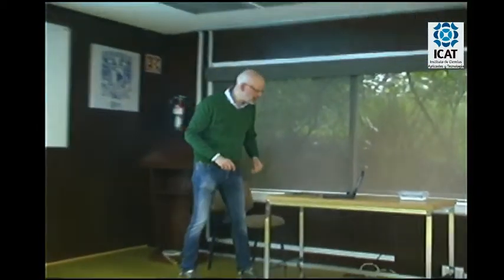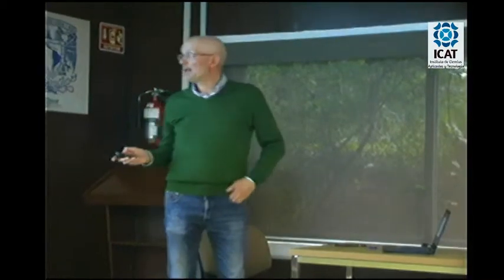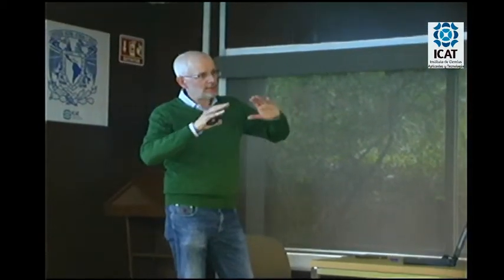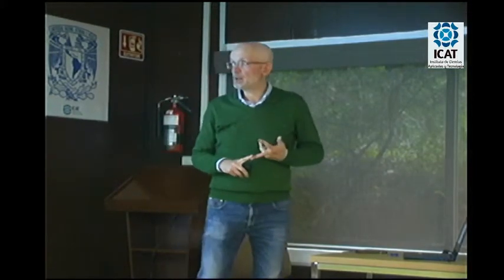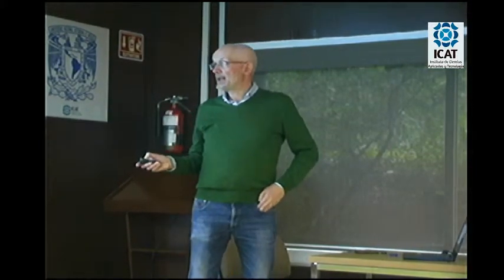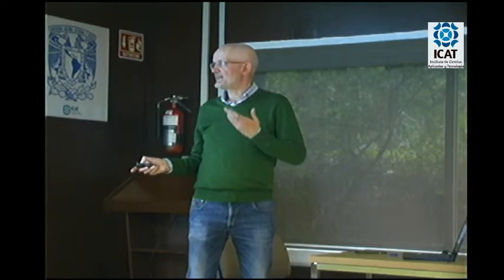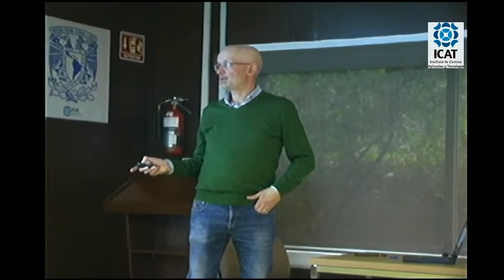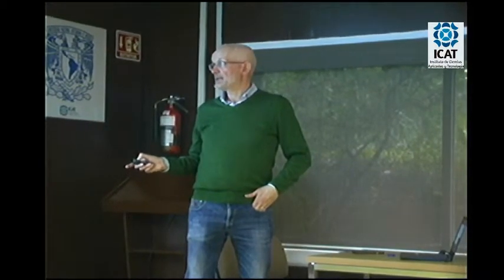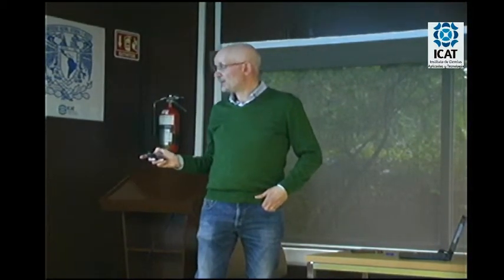Okay, so I don't think we actually have a machine, and there are different approaches to how you melt. You can melt by CO2 laser, and this is a way you can control quite nicely. You can melt with a flame, and you can melt with arc discharge. We were using arc discharge, because of our background in using a fiber splicer. And basically here is what we implemented.